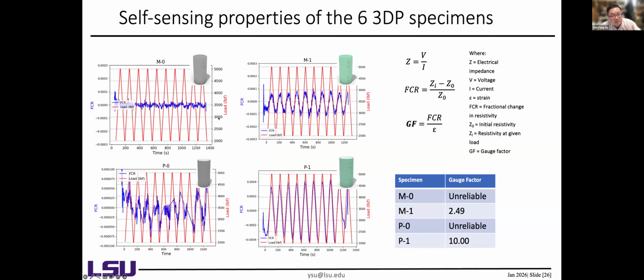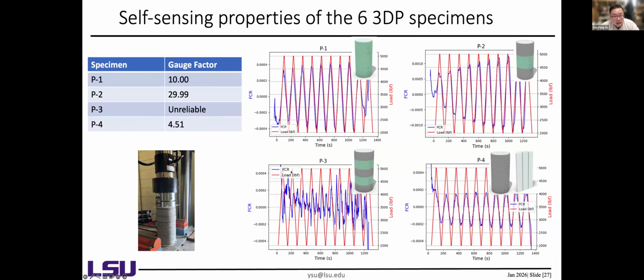Apparently, if we incorporate this self-sensing concrete, we can see the change of the signal along with the cyclic loading. And for the 3D print formwork, we can see a really good relationship between the cyclic loading and the signal, and the gauge factor is around 10. We also find that for this P2, if we only incorporate this material in between, in the middle of the structure, we can also observe the signal. And in the middle, as an internal core, we also obtain a good correlation.